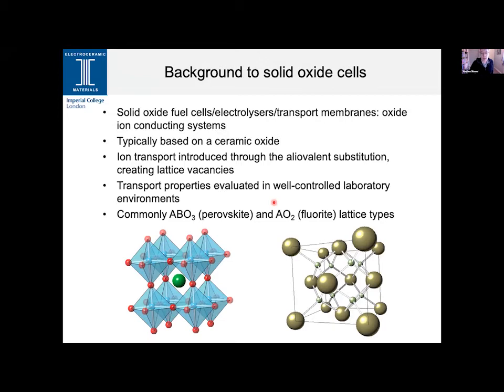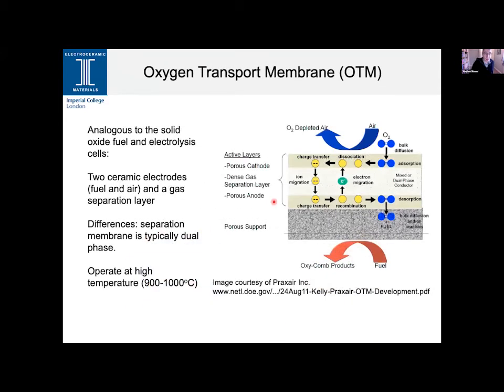So what I want to focus on really is the work that we've been doing on oxygen transport membranes. And so this is essentially a device which is analogous to the solid oxide and solid oxide electrolysis cells, in which case they have two ceramic electrodes, so a fuel electrode and an air electrode. And for the oxygen transport technology, we have a gas separation layer, which is analogous to the electrolyte in the solid oxide fuel cell. The key difference really is that gas separation layer, the membrane layer, is typically a dual phase mixed conducting membrane. The other fundamental difference is that these are typically very high temperature of operation devices, so operating typically at 900 to 1000 degrees C.